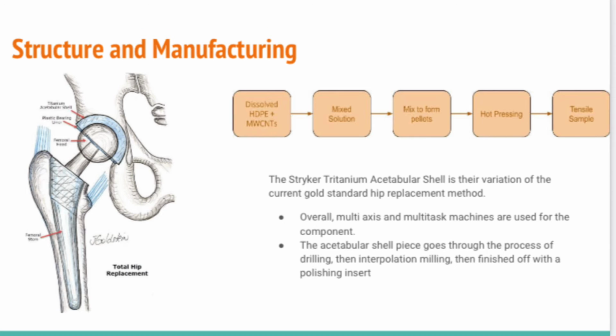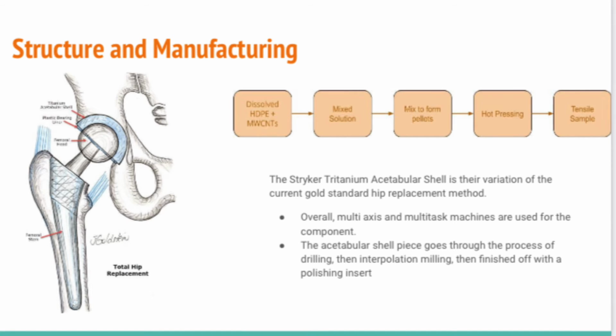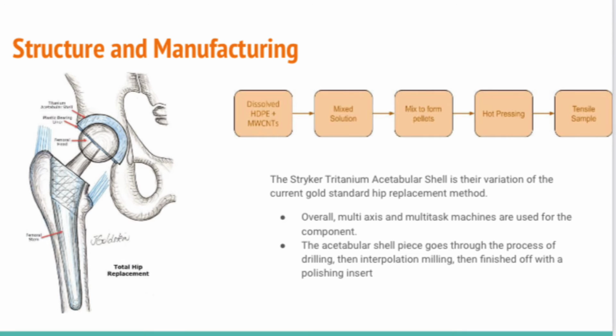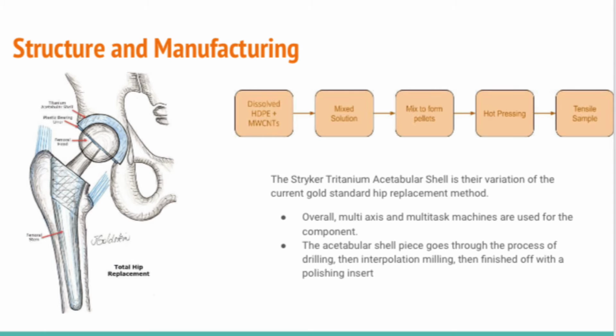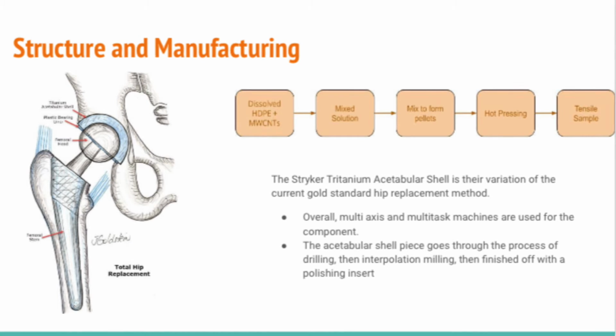For the structure and manufacturing of joint replacements, specifically metal on plastic hip replacements, there are 2 parts to analyze: the plastic part and the metal part. For the plastic part, start by dissolving HDPE, which is a high-density polyethylene, which is also a thermoplastic polymer made from petroleum, and MWCNT, which is a carbon nanotube. And due to the planar honeycomb lattice of the carbon structure, MWCNTs are considered to be the ultimate high-strength fiber. So when mixing the MWCNT with the HDPE, the expectation is that the composite will be strengthened.